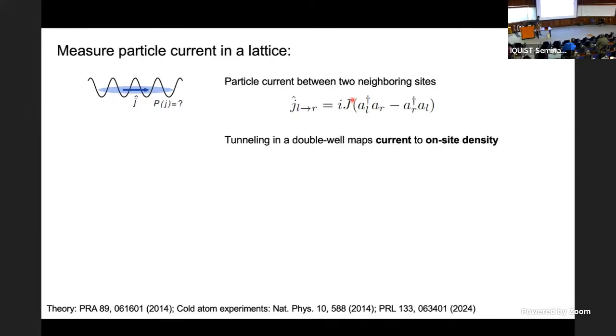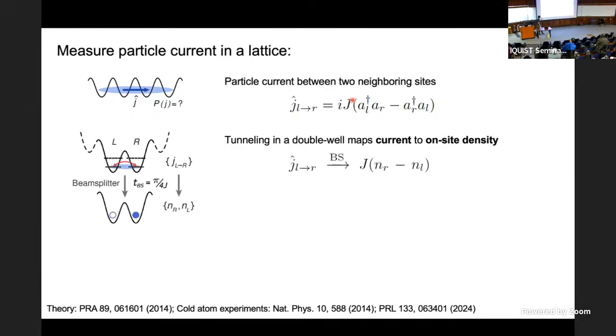The way we measure this is actually using a trick where we map the current to density, okay? Because density is what we measure eventually with these readout resonators. It turns out if you isolate just these two middle sites, while keeping the tunneling on, and you wait a quarter of the period of the tunneling, you map current to density. If you want an analogy, think about a harmonic trap. Wave function in a harmonic trap, a quarter period maps position to momentum and momentum to position. And this is very similar. Okay. Some little additional caveats, which I'm going to skip.